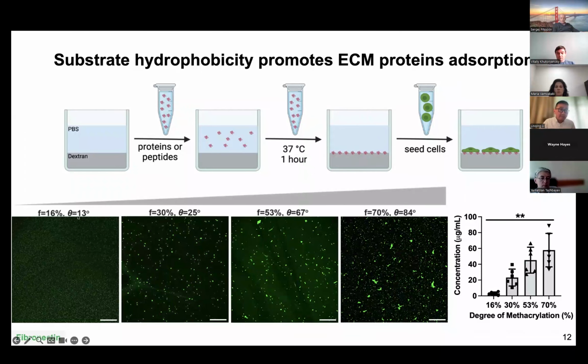So now you can see that F is indicating the modification, theta is indicating the contact angle, and you can see there's a direct correlation between the modification of the methacrylation as well as the contact angle. As you increase the contact angle, you have an increased amount of adsorption of fibronectin.